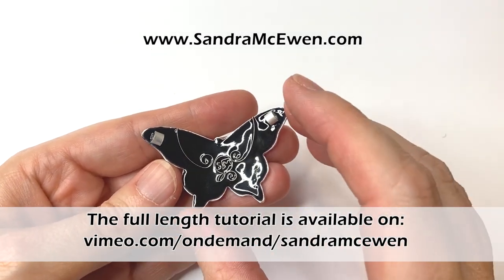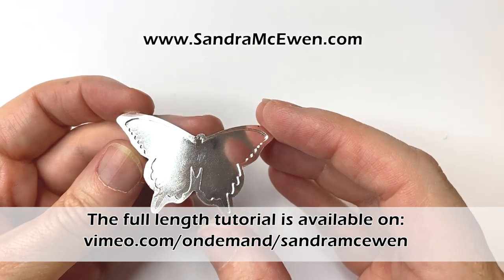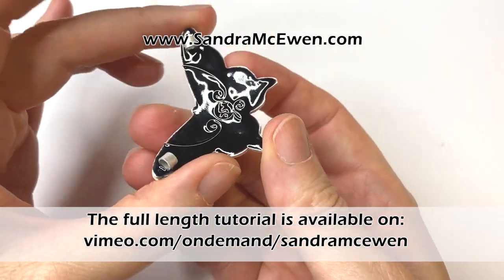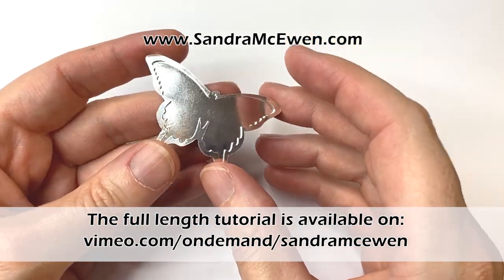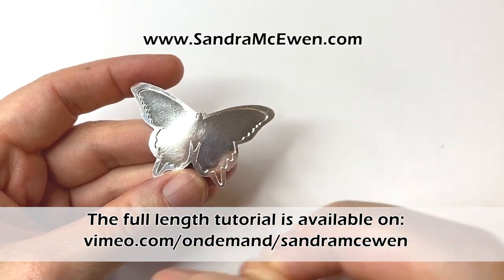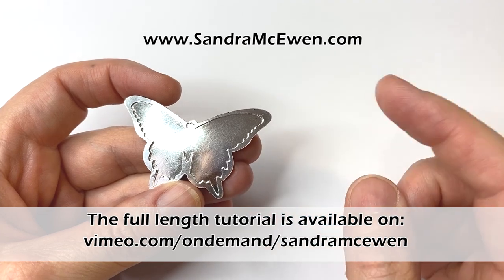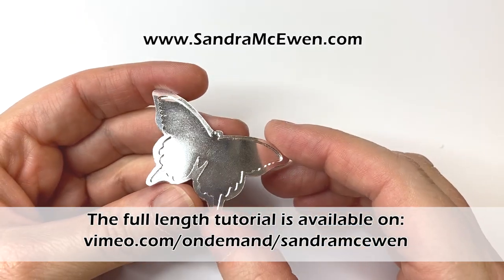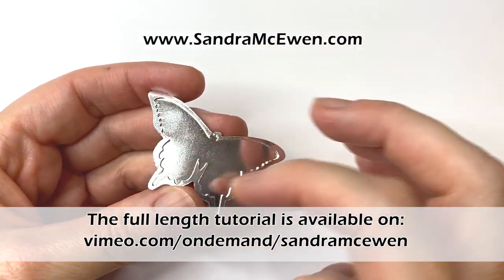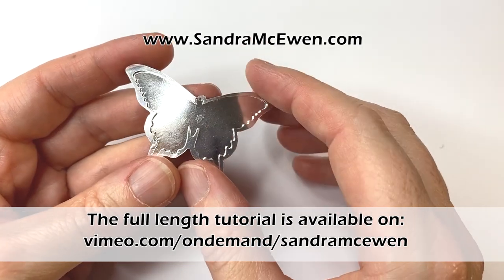The back is ready to go, and now we can start thinking about the front. You might be thinking: why didn't you do the texture before putting all this enamel on the back? Because there's a lot of enamel on the back and exactly zero on the front, so you do run the risk of cracking from the pressure. The reason I don't add texture first is that sometimes in the kiln things get heated up and your enamel goes kind of white and matte — it doesn't happen all the time, but enough that it's frustrating if you've already put a beautiful texture on there. So I like to leave the option open to sand or polish if needed. But we can see it's still nice and shiny, so we don't have to worry about that this time.